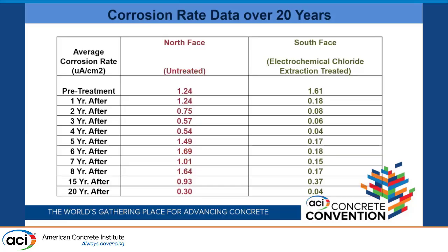MTO also did corrosion rate measurements out there using linear polarization. The results parallel the corrosion potential data. On the untreated face, the corrosion rates really didn't change very much. I mean, there are seasonal changes because of weather conditions, wet, dry, hot, and cold, even though they went more or less at the same time of year. But on the treated faces of the pier, the corrosion rates dropped in a very significant way.